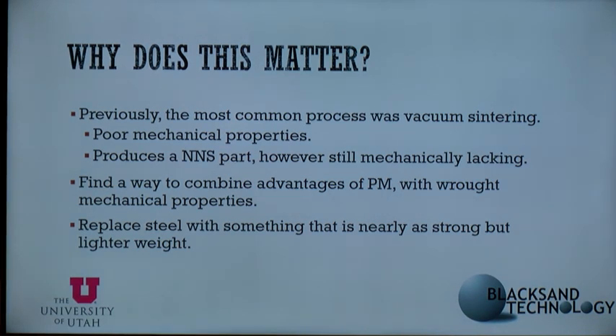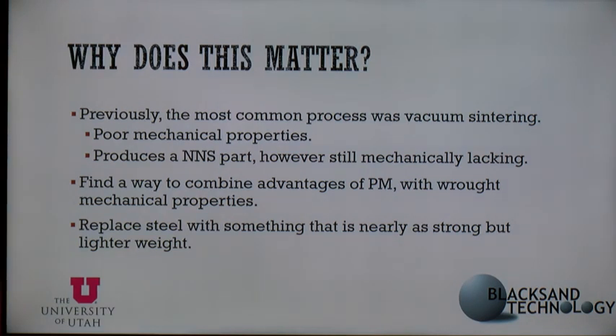If titanium gets in contact with oxygen, it'll immediately become titanium oxide, essentially, and it'll start to form layers, and it just becomes not a good material. So we want to keep it titanium, not titanium oxide. So it has to be sintered under either high vacuum or argon. But previously, the issue with this was it has poor mechanical properties. The advantage is that it has near net shape to the parts, it's closer to the end shape, and so you get savings due to that.